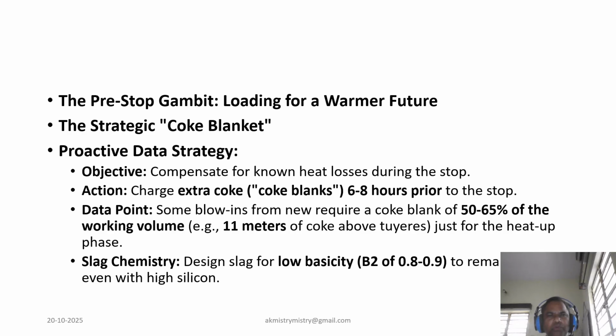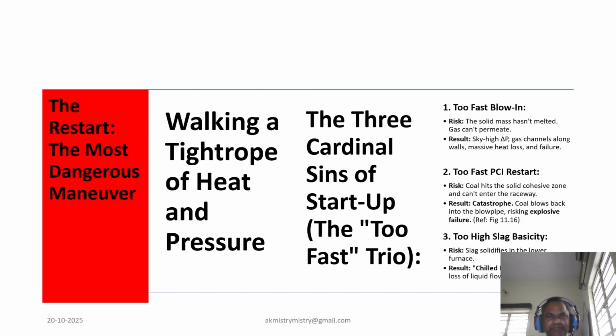Now, coming to the furnace for a restart. If the stop is critical, the restart is the most dangerous activity. This is a delicate walk on a tightrope of heat and pressure. And there are three cardinal sins, a deadly trio of "too fast" that can doom the entire operation. Sin number one, too fast a blow-in. The risk: the solid mass inside hasn't melted yet. Gas cannot permeate the frozen burden. The result: a sky-high pressure difference, gas channels violently along the walls, massive heat loss, and total restart failure.